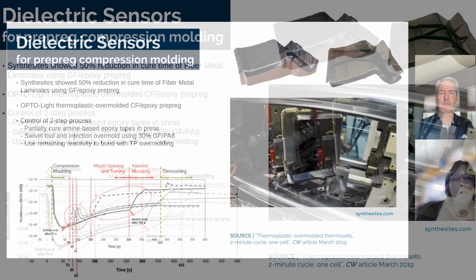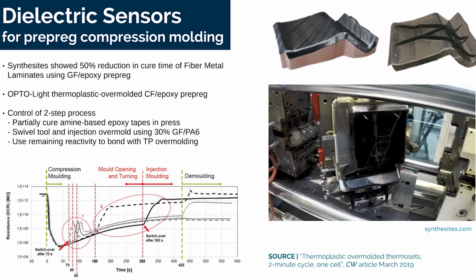Another use of dielectric sensors is not just in liquid molding, but in prepreg molding. So one of the projects they did is working with fiber metal laminate. So that would be GLARE, where you alternate the aluminum and glass fiber epoxy prepreg as a fuselage material. And they were able to drop that cure time by 50%.